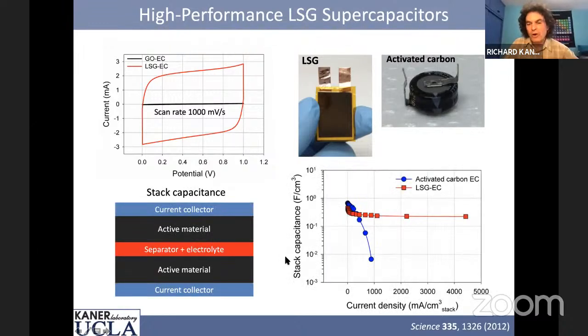And so we can compare our material, the stack capacitance versus current density, and you can see this versus a commercial material. So in blue is the commercial material and red is our material. And at low current, they both look pretty much the same. But as you run them harder, the commercial material will eventually fall off and our material will still keep performing. And so we can run this above 4,000 milliamps per cubic centimeter.